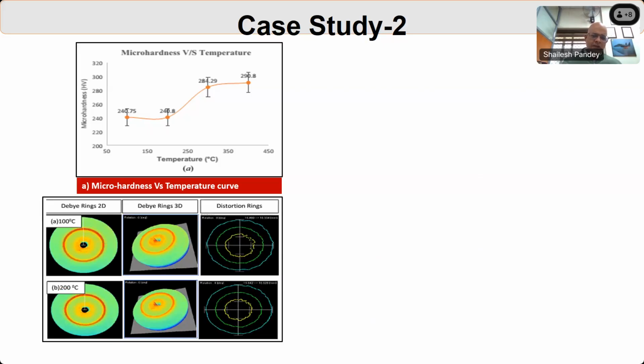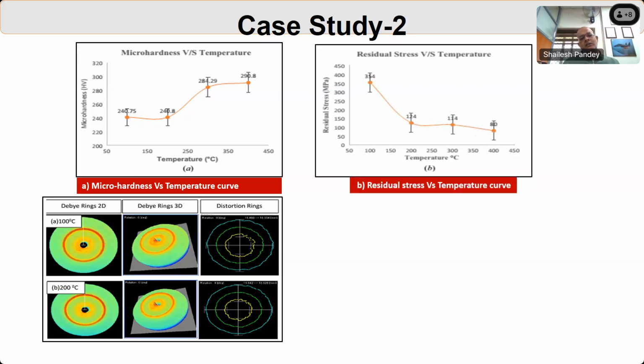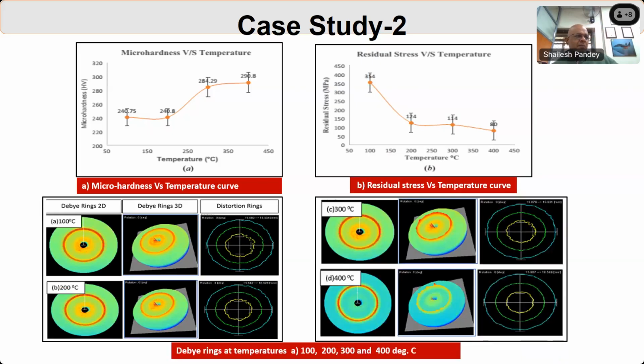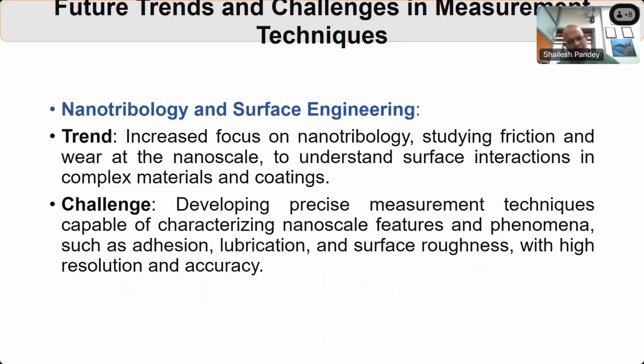And this microhardness can also be seen with the help of XRD, and with the help of XRD, the residual stress is decreasing with the increase of temperature. It means that while we are increasing the temperature, the stress relieving process is happening.